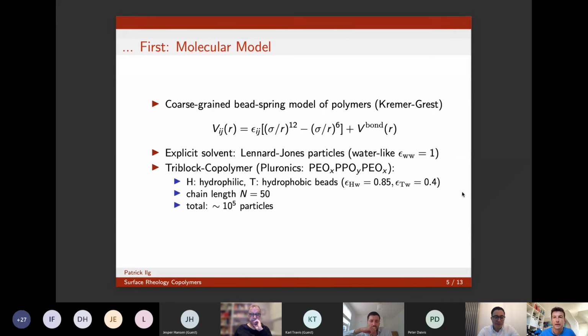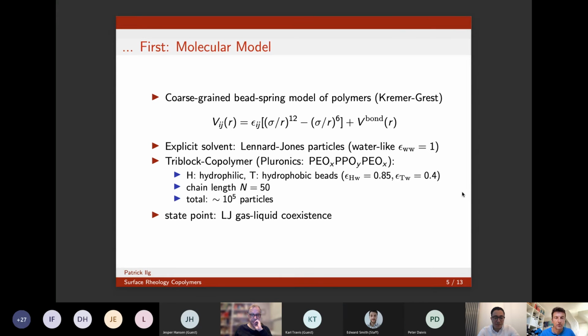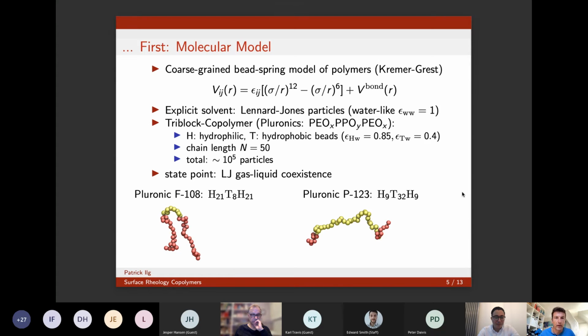We model this by different values of the Lennard-Jones interaction parameters with the water molecules. We look at rather short chains of 50 beads and have a reasonable sized simulation. We do that at the Lennard-Jones gas-liquid coexistence point so that we have a liquid-vapor interface. So the molecules we are looking at, we take 2 of them. One on the left has 21 hydrophilic beads and a shorter middle block, whereas the one on the right is the opposite, shorter heads and a longer middle. These pluronics we took because they are commercially available, and Ahmad wants to do some experiments as well, so that's very convenient. And they are used as emulsifiers, detergents, etc. So they actually have some use, and they are sufficiently simple.